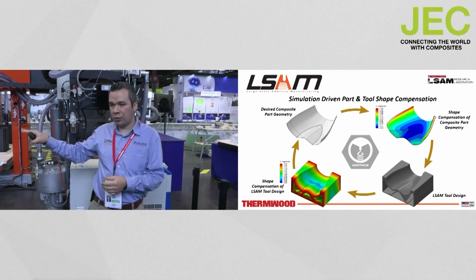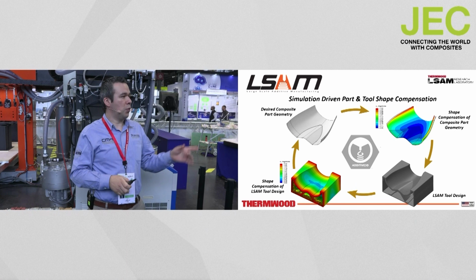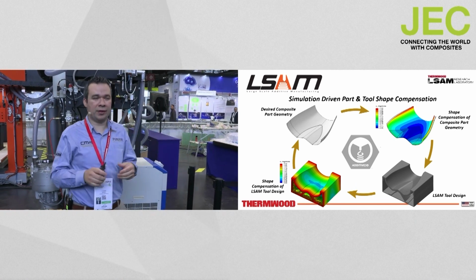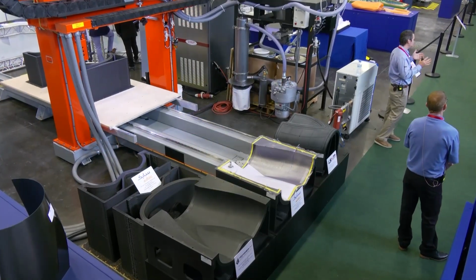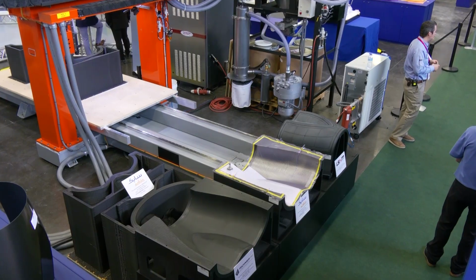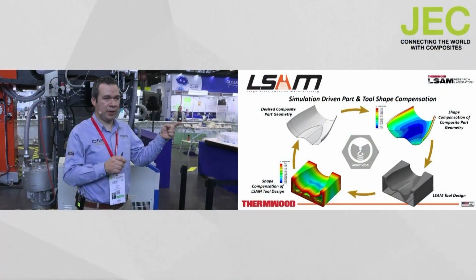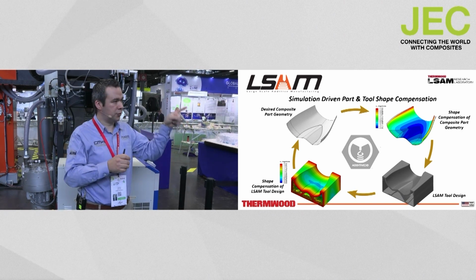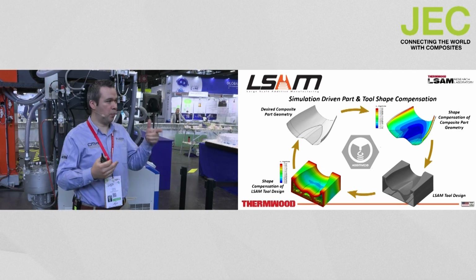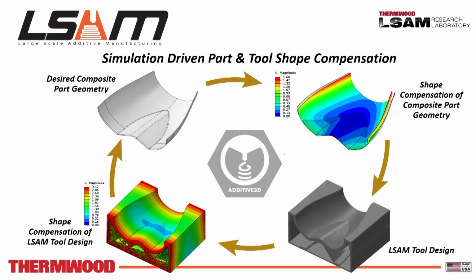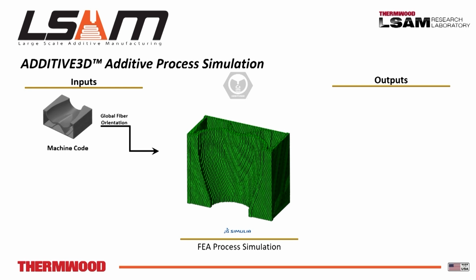Now, elaborating a little more on this example that we're demonstrating today. We did basically a full circle of simulation-driven design, where we first started with the desired composite part geometry, which was inspired by the X-59 aircraft. Then we predicted the shape change of the composite laminate, you know, the spring back that everyone here is familiar with. Then we designed a tool for the LSAM process. We predicted and compensated for the shape change of the tool, and then we do a fully integrated simulation where we consider the part manufactured on the printed tool and verify that we in fact produced the desired composite part geometry.